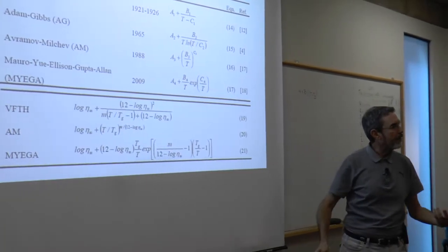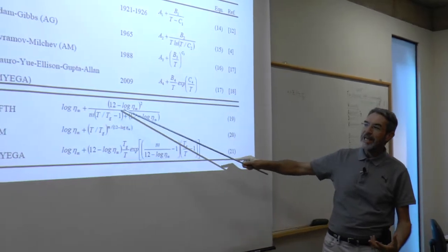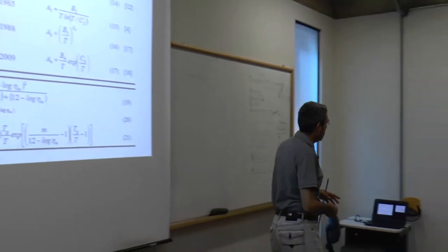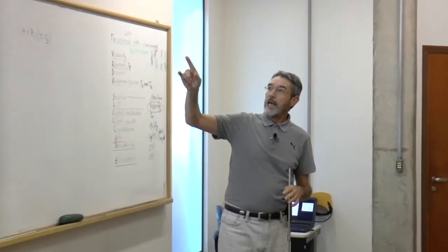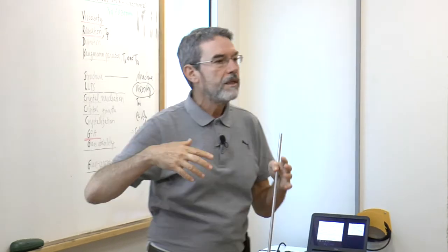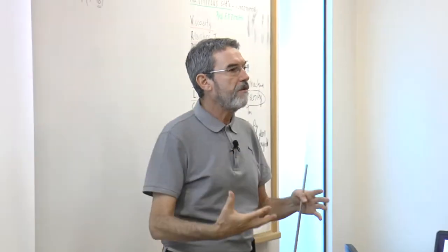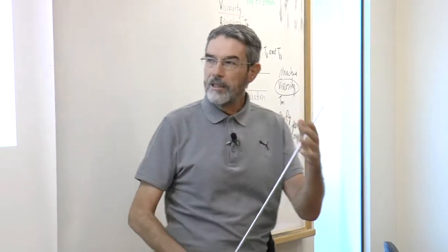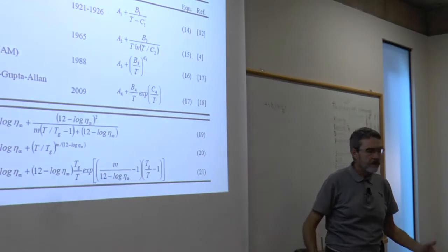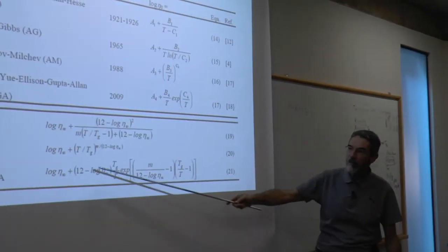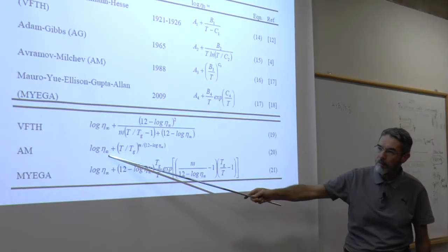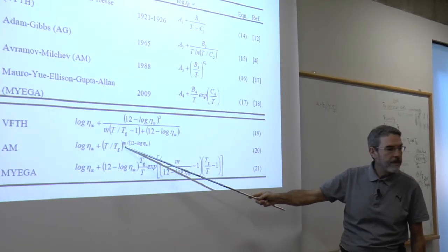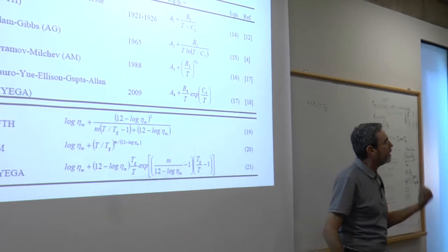So it's much better to read that same equation in this way, because now we can relate A1, B1, and C1 to physical parameters, which have a meaning: fragility, eta infinity, and Tg. And the same can be done for all these equations. So the Avramov equation is written in this form. Again, eta infinity, Tg, and m. So there are 3 parameter equations.